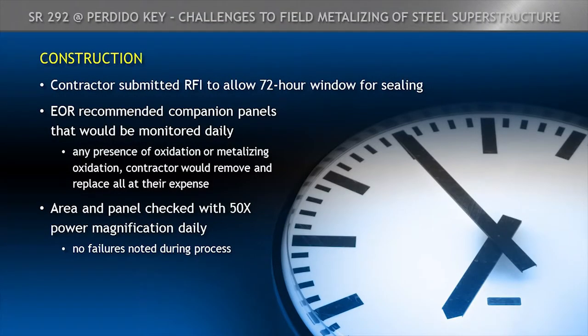We talked a little bit about the metalizing sealer recoat time. One of the concerns is that you get the sealer on the metalizing in time to prevent any oxidation of the metalizing. And the contractor actually submitted an RFI to allow for 72 hours. When we thought about it, we actually came up with a plan that the FDOT people in District 3 were okay with, and we actually did companion panels at the time.